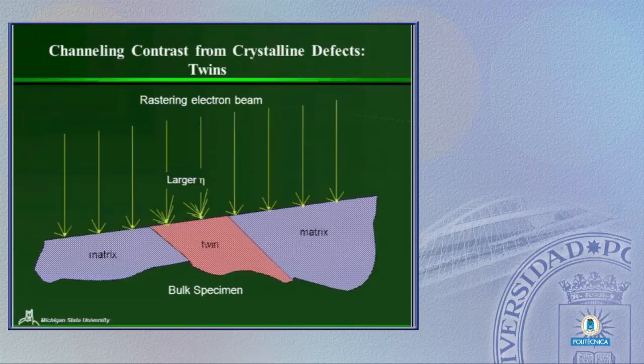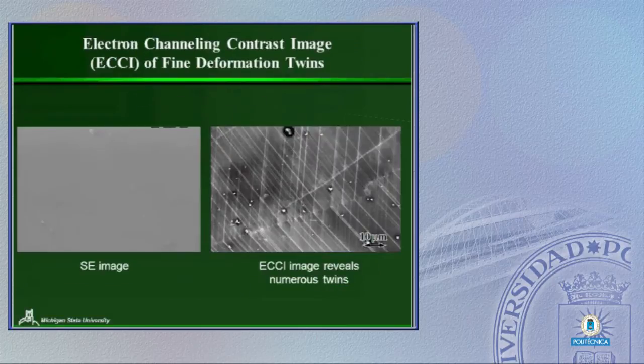So if we look at the sorts of things we can do, I think we can imagine now that if we could see contrast from different orientations in a polycrystal, we could certainly see contrast from different orientations associated with twins. As we move across a twin, when the orientation changes, we're going to get a change in that backscattered yield, which is going to reveal the twin. But we can actually do that with pretty good resolution.